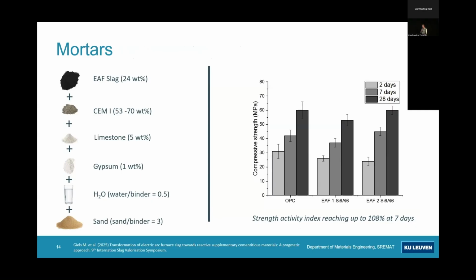So then the final question, which for the cement people is the most interesting: is it now working? Can you make it amorphous with these small additions, and is it actually reactive? And once we make mortars, ideally we have similar strength with respect to the Portland cement reference. We tested this for 2 slags, and actually the optimum was the same for both slags, and we saw you can get strengths comparable to Portland cement.